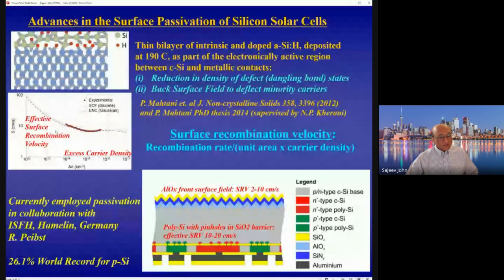And they've shown that this recombination velocity can be down to about 10 centimeters per second. And just for comparison purposes, if they did nothing to the surface and left the surface unpassivated, that recombination velocity would be on the order of 10^6 centimeters per second. So this is a great reduction in the recombination rate.